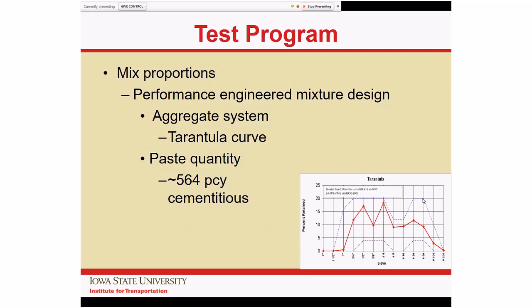For the mixture proportions, the approach we're using in the PEM program is to first look at the aggregate gradation. So we optimized the gradation for the materials that we had in order to stay inside the tarantula curve, and we managed to do that. We also limited the paste quantity by limiting the total cementitious material to functionally a 6-sack mix. We may have been able to pull it down a little further, but we settled on a 6-sack mix, as that is fairly typical of what happens out there. And again, this is based on guidance from the literature that we don't want to have too much paste in the mixture.